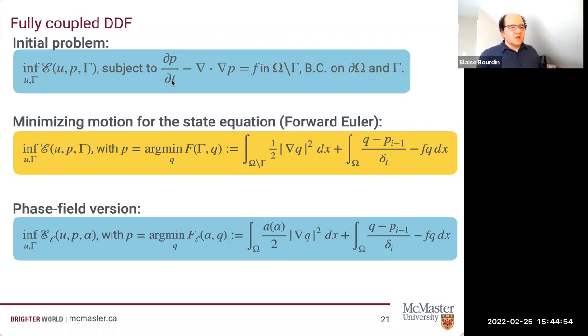Quickly, if you want to do a little bit of mathematics on this problem and solve the fully coupled problem, everything that I've shown so far was a one-way coupling. That is, I was not really accounting for the crack geometry in a heat transfer problem. So let's go back to our diffusion-driven fracture problem. So we want to minimize some energy that depends on U, the displacement, P, the diffusive field, and gamma, the crack, subject to a state equation, which is a parabolic equation, in a domain that itself depends on gamma.